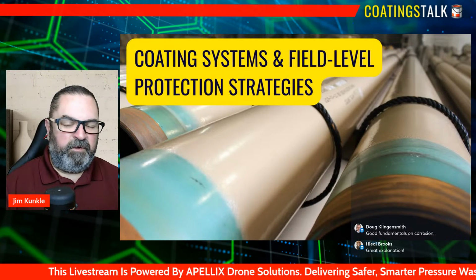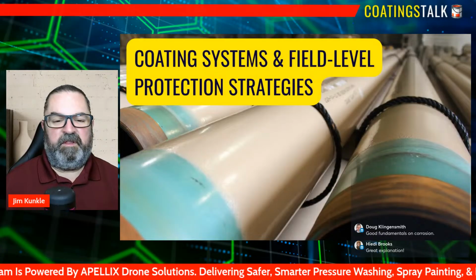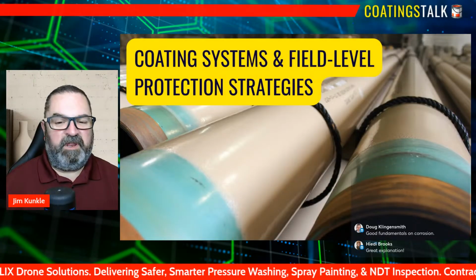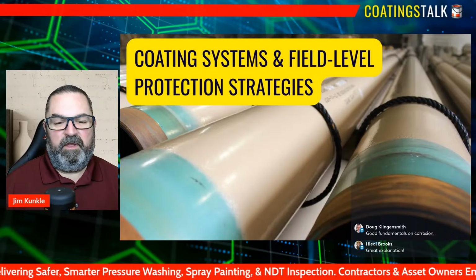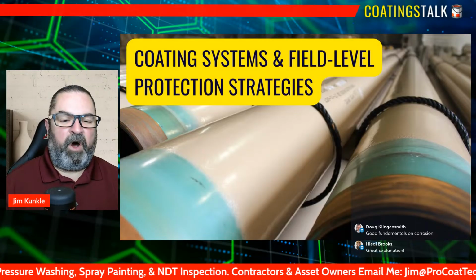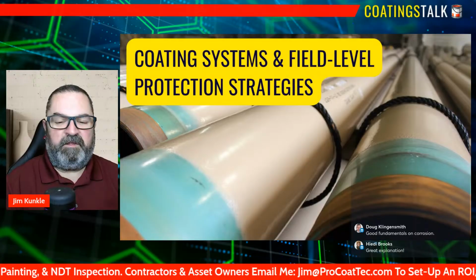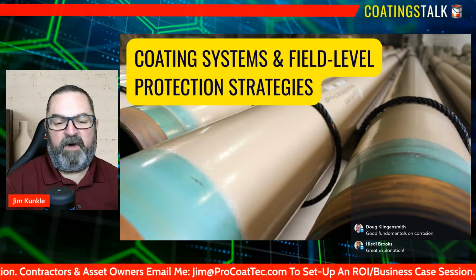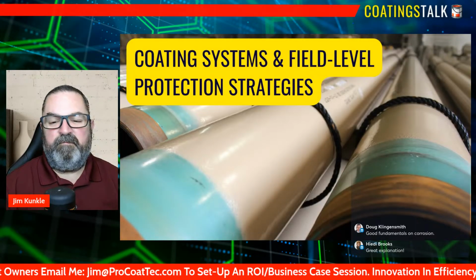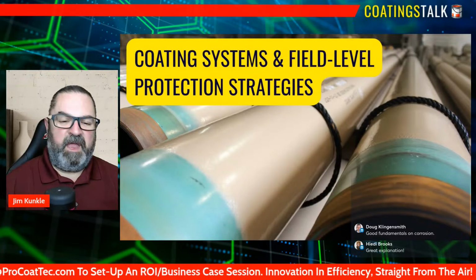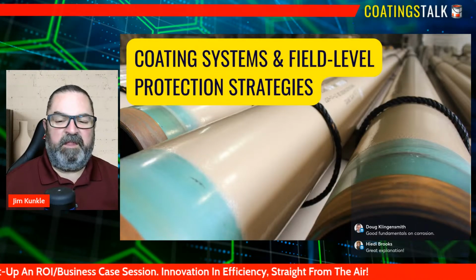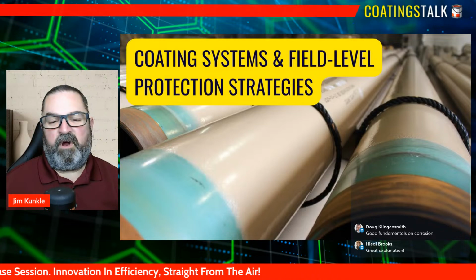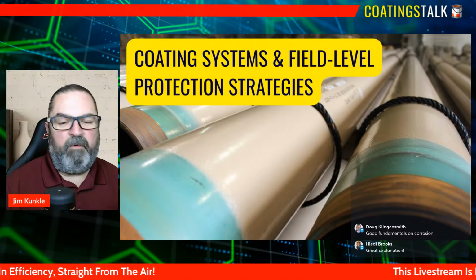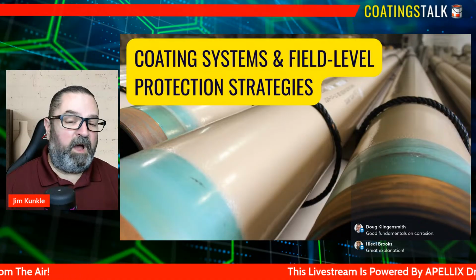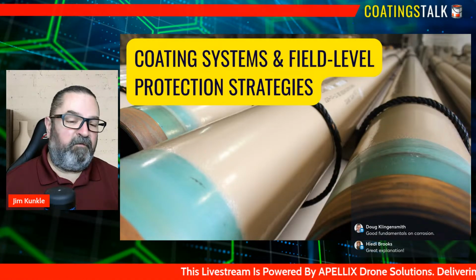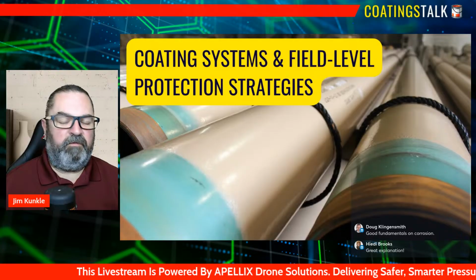If contaminants, mill scale, rust, or salts remain on the steel, they create weak points where corrosion can immediately restart beneath the coating. Even the most advanced coating chemistry cannot bond properly to a dirty or poorly profiled surface. A clean, dry, correctly profiled substrate gives the coating something to bite into, creating mechanical adhesion strong enough to withstand surface conditions. And when surface preparation is rushed or compromised, the coating may look fine on day one, but adhesion loss, blistering, and under-film corrosion often follow soon after.